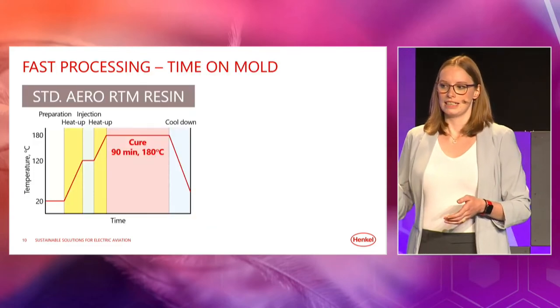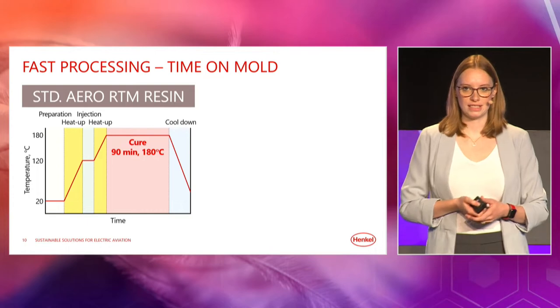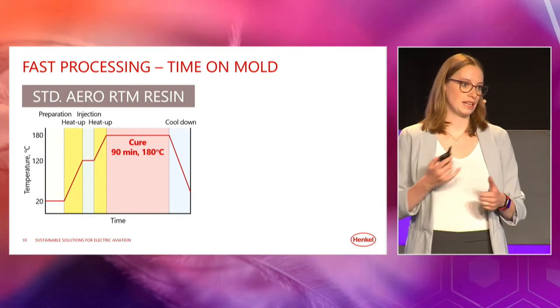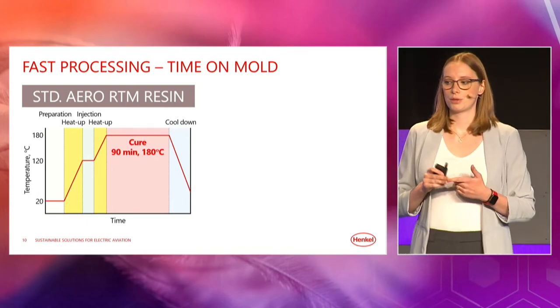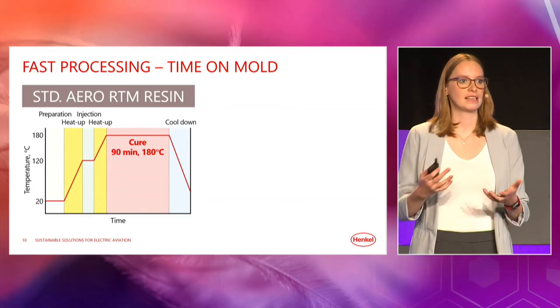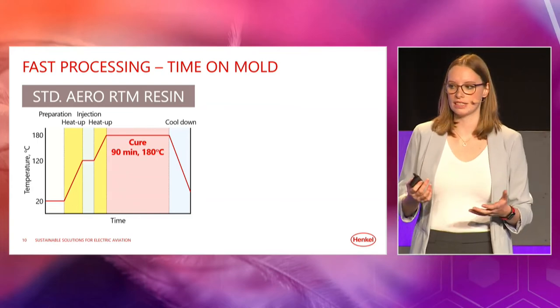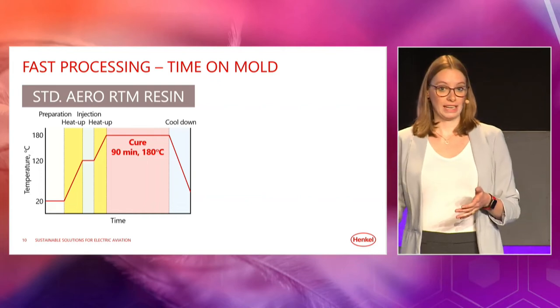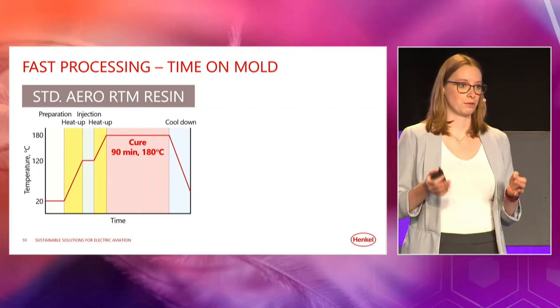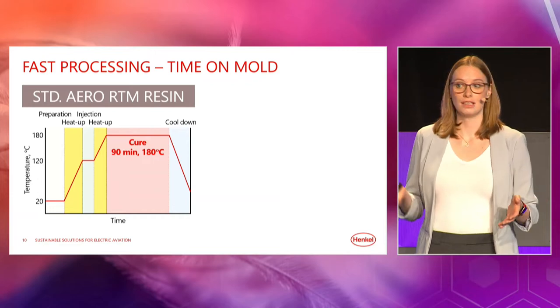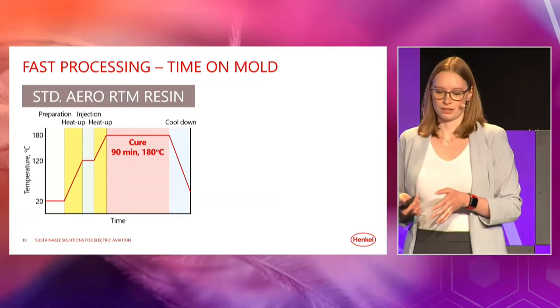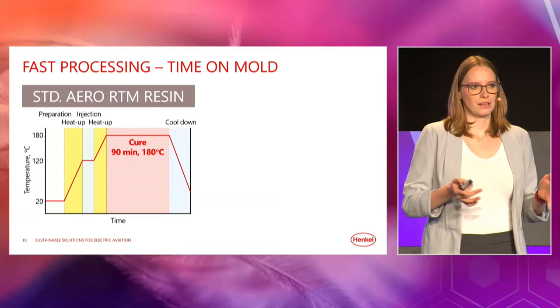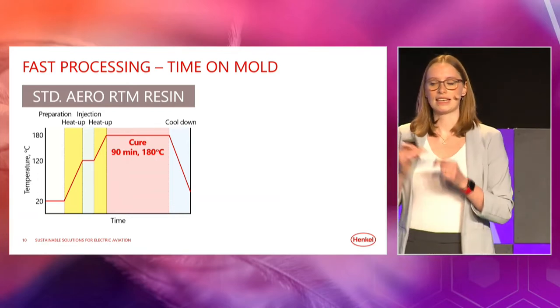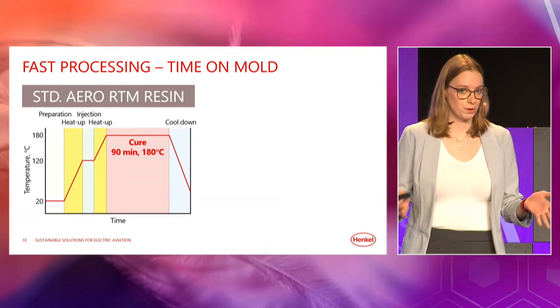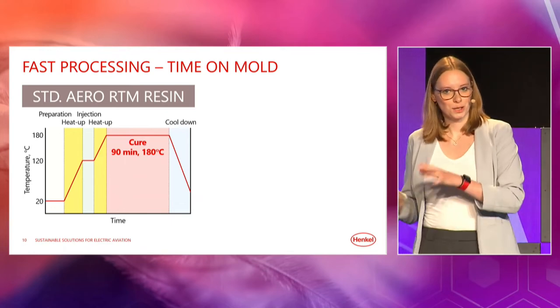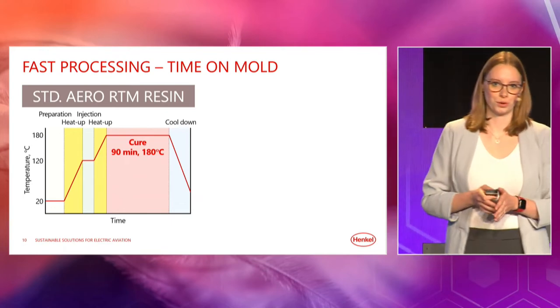Looking at a standard Aero RTM resin system, it needs to be preheated to 80 degrees C, and the mold is preheated to 120 degrees C. Then the resin is injected. Everything is heated up to 180 degrees C, and it needs to cure there for 90 minutes to reach the final mechanics. Then it's cooled down. So we sat down and thought, okay, the bottleneck is really there. It's the 90-minute cure on the mold. What can we do about it? And the answer is quite easy: reducing the cure time on the mold.